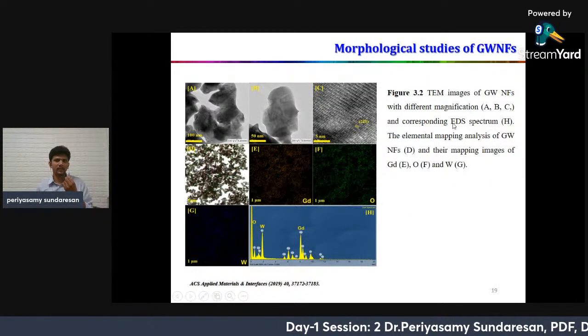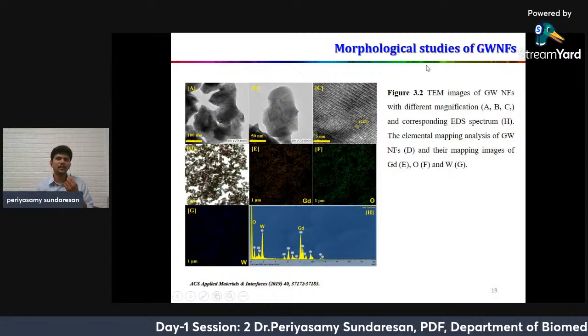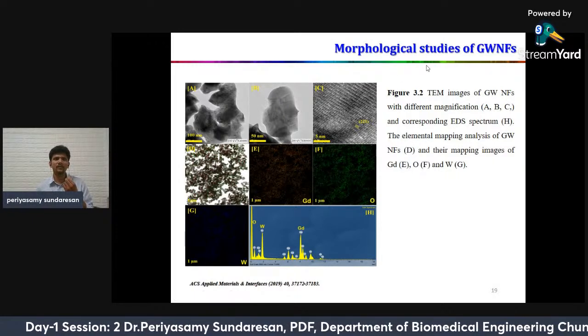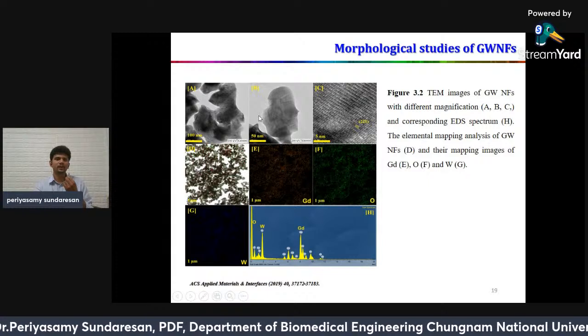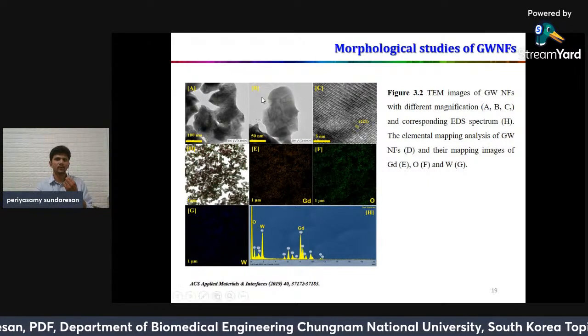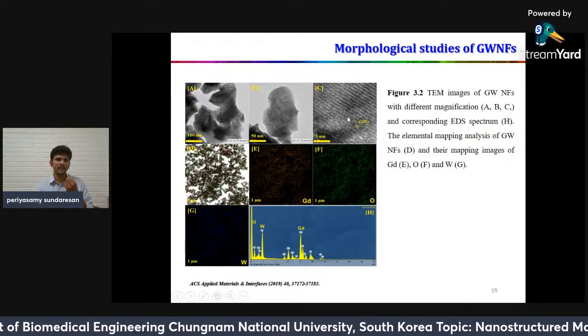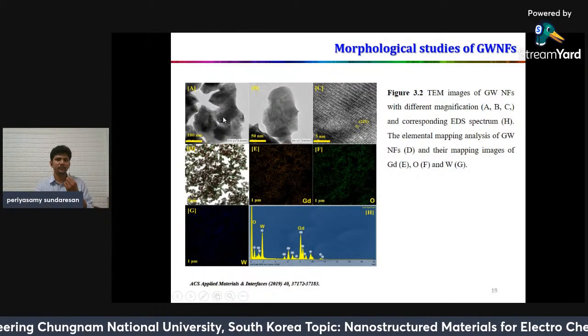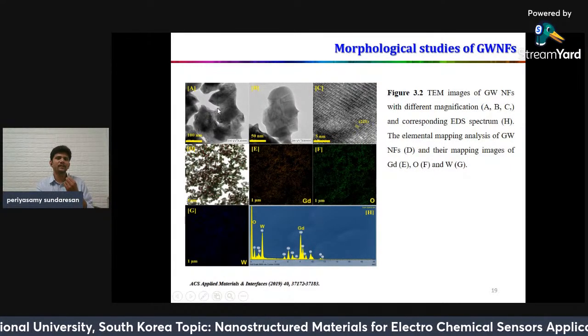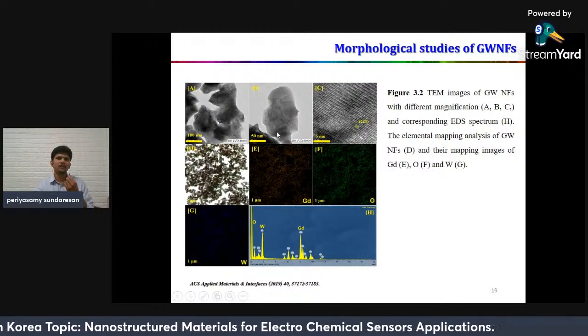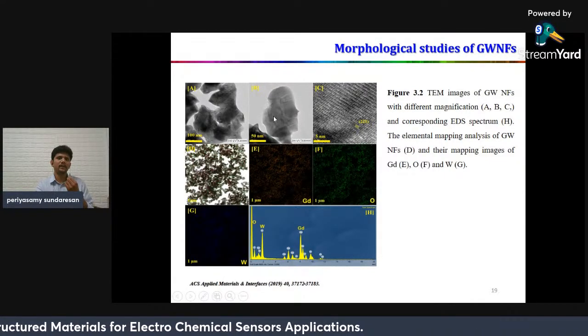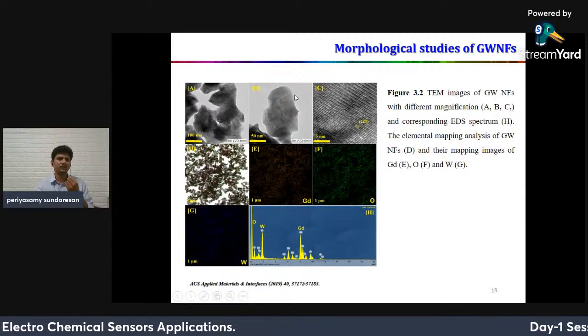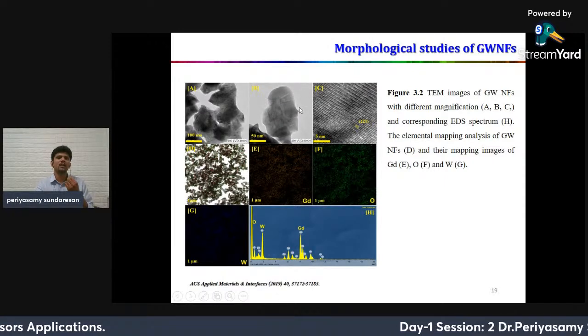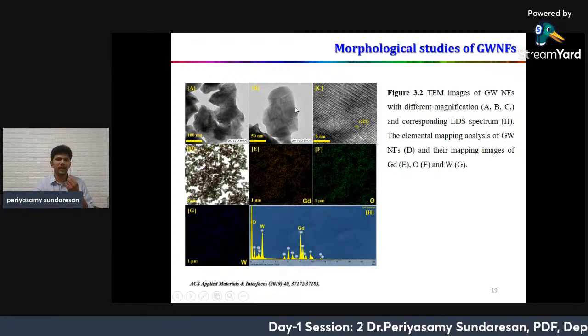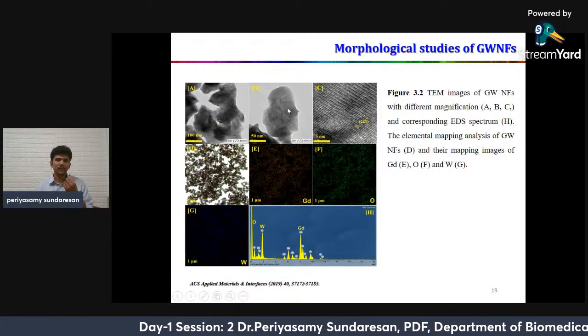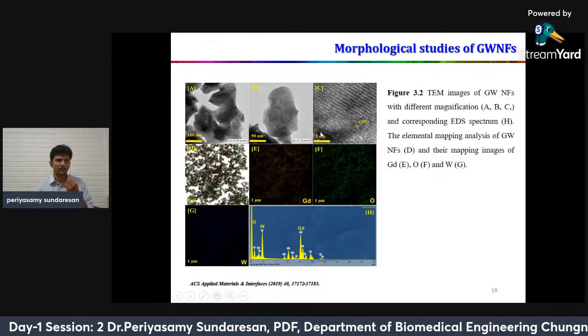This is the first characterization. The morphological studies of the gadolinium tungstate nanoflakes. After preparing the gadolinium tungstate, I checked with FESEM and TEM analysis. The first one is a TEM analysis image. I have seen nanoflake-like structures. We are seeing flake structures appear. It means it has a two-dimensional structure. We get a two-sided active area, so the prepared catalyst can be applied for the electrochemical sensor.